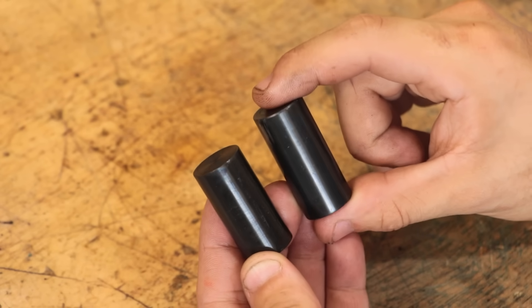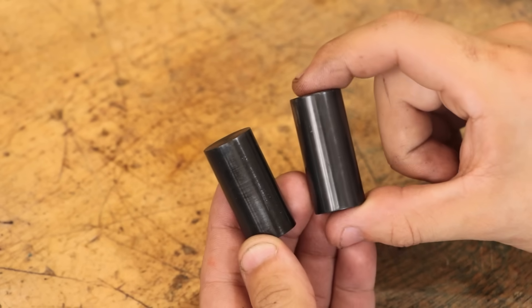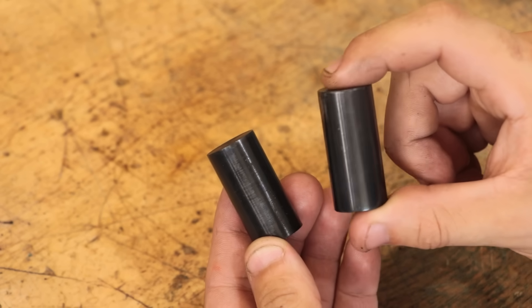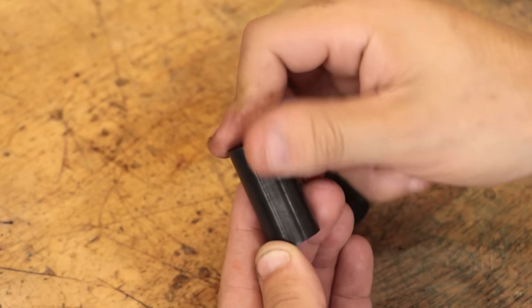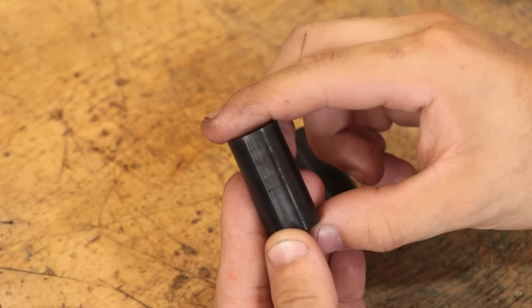Now I have found that it does stick a bit better if you stick to say 120 grit sandpaper, it gives the coating something to bite into. But then again you are going to be sacrificing the surface finish and you will see that brushed finish show through on the final part.